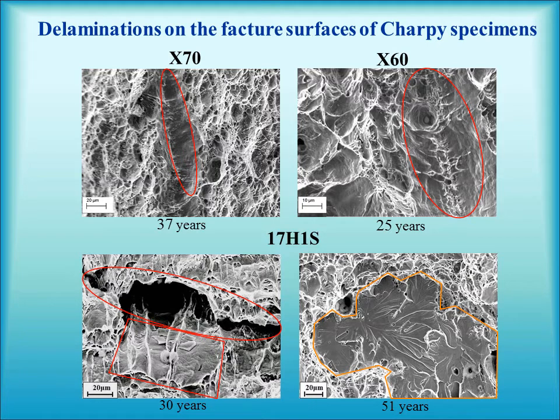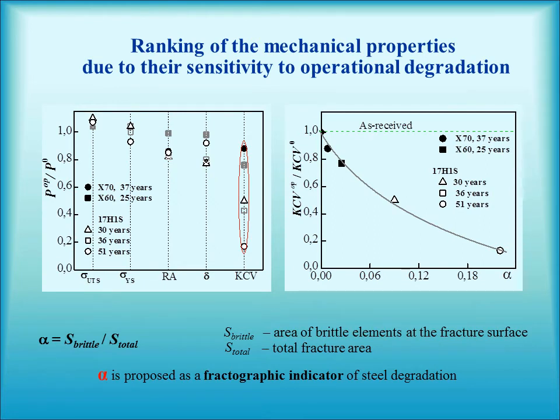Considering the fracture surfaces after the impact tests, some fractographic elements of brittle fracture were identified, namely non-structural smooth areas, delaminations, indicated in red, against the background of a typical relief of ductile fracture due to microvoid coalescence, and cleavage with typical river patterns, right bottom picture, and also their combinations. Comparison of the mechanical properties regarding their sensitivity to operational degradation allows concluding that impact toughness is much more sensitive to in-service changes in material than strength and plasticity. So it was chosen for the following materials characterization.